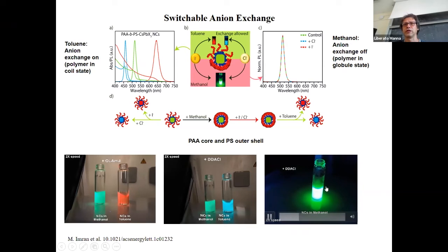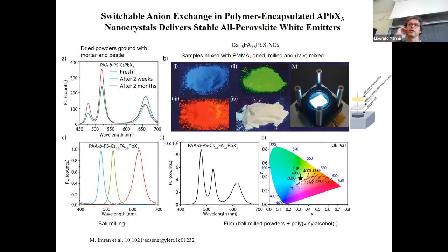But then as soon as you add toluene to this flask, you will switch the polymer from the globule to the coil state. And what will happen is that an ion exchange is triggered. You will see now that toluene is added, and the color of emission shifts from green to blue.